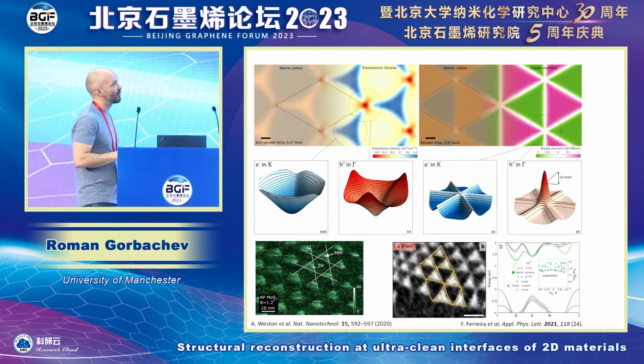And so just to summarize, in terms of twistronics and TMDs, there are two very different systems, and that is where you align your layers either parallel to each other or at 180 degrees. In one case, you achieve a controlled network of quantum dots. And again, there are a lot more papers recently on this topic. And in the other system, you achieve a system with broken inversion symmetry, where you have ferroelectricity, where you have polarized wave functions, and that can be really employed in some high-end electronic applications.